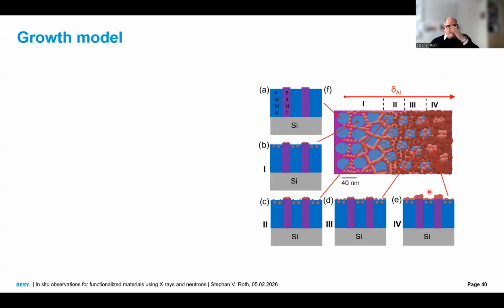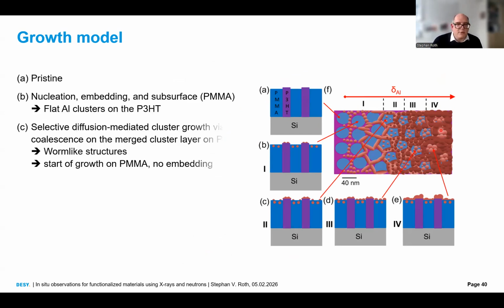This leads us to the point that we can establish a growth model. This is one of the decisive advantages then of GISAXS, that we can find out all these growth models. We have these nanostructures. Here's the side view. Here's the top view of our diblock copolymer film. We have these aluminum nanostructures growing on these worm-like P3HT structures. They first grow together on the P3HT, and then they start to grow together on the PMMA. And in the end, we have this nice fully percolated electrode. Good.